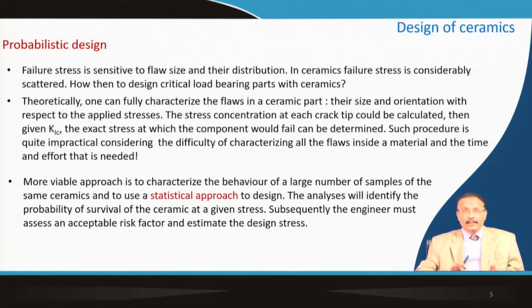So, failure stress is sensitive to the flaw size and their distribution. In ceramic, failure stress is considerably scattered, exactly as I have shown. So, how to design the critical load bearing structure using ceramic material, how can you design it?